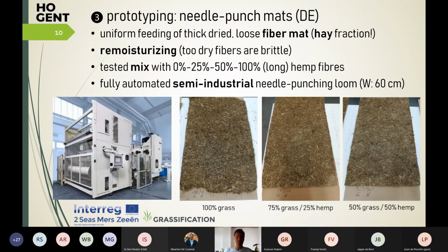A third type were needle-punched mats. They were produced on semi-industrial equipment in Germany, with a needle punch width of about 60 centimeters. We tested several combinations of grass and hemp fibers. Important to note is that we had to re-moisturize the grass because the dry fibers are too brittle.